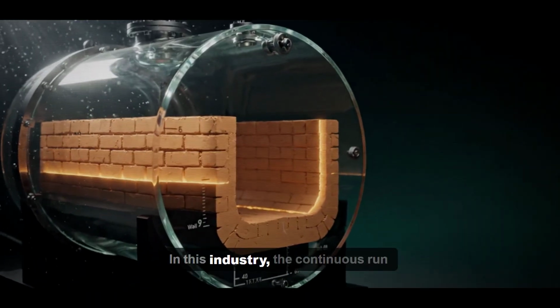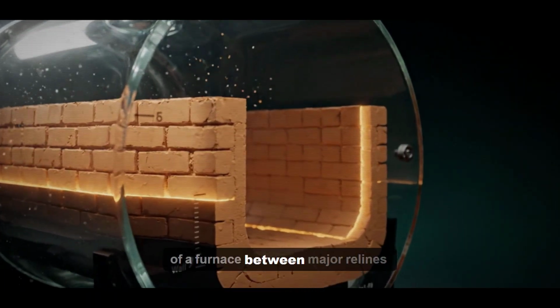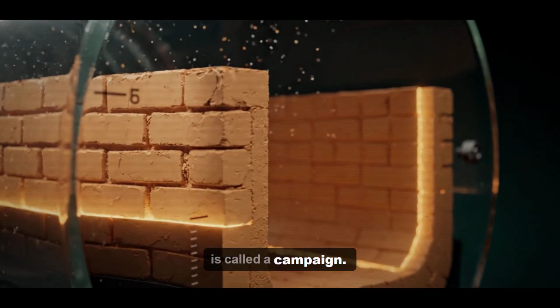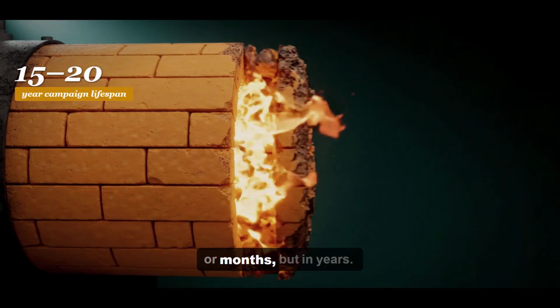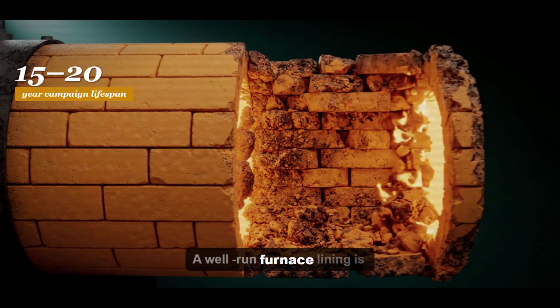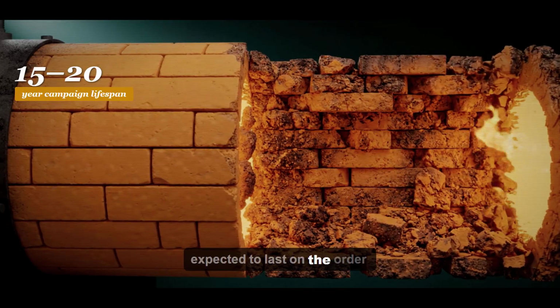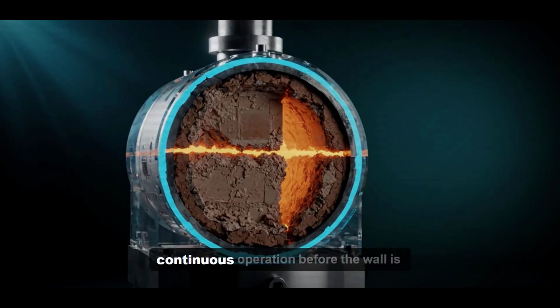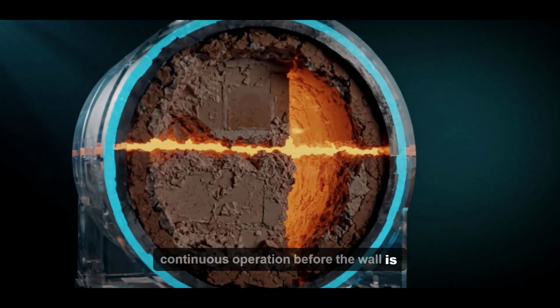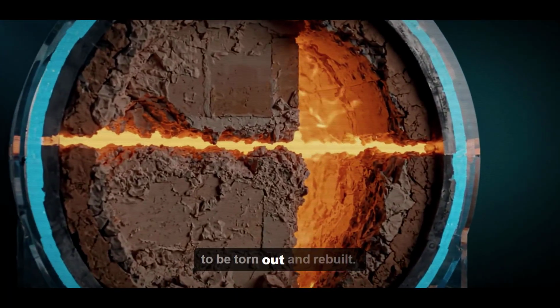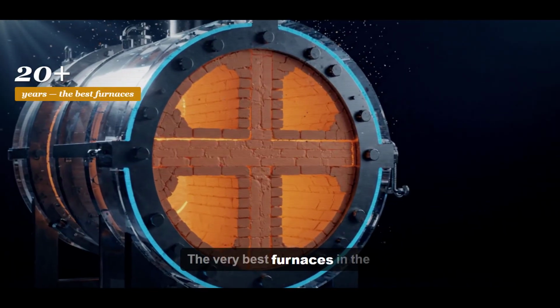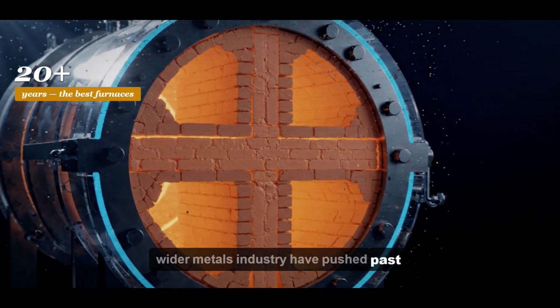In this industry, the continuous run of a furnace between major relines is called a campaign. It is measured not in days or months, but in years. A well-run furnace lining is expected to last on the order of 15 to 20 years of continuous operation before the wall is worn thin enough that it has to be torn out and rebuilt. The very best furnaces in the wider metals industry have pushed past 20 years.